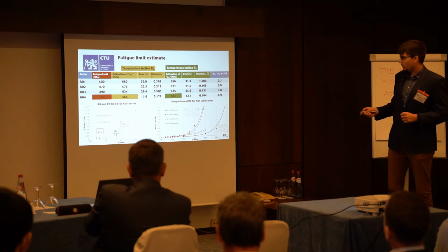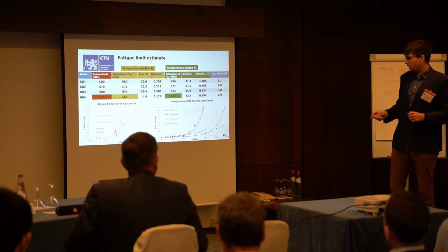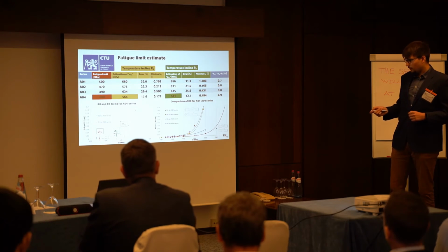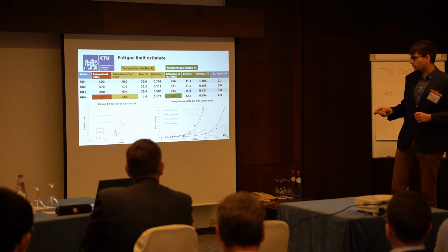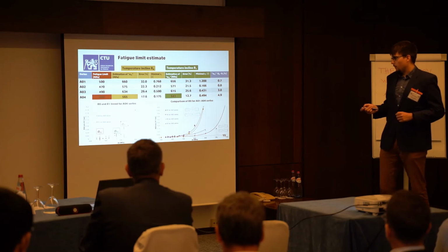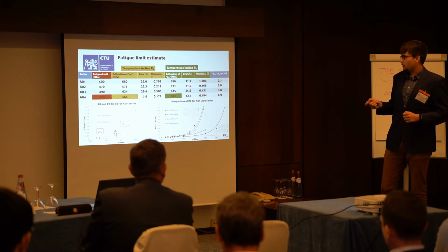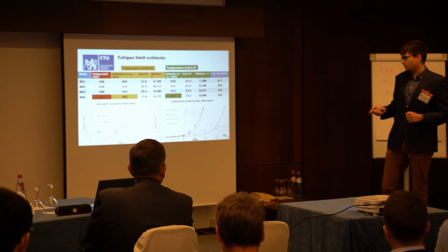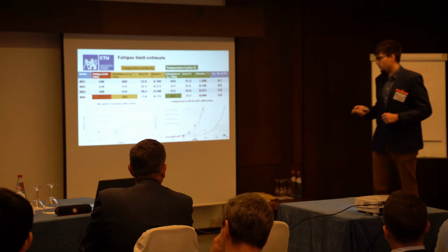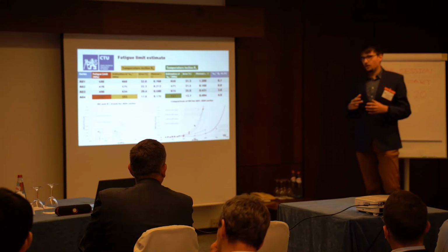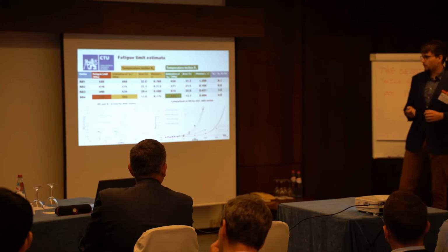On the right side, you can see the evolution of the initial incline for the dog bone specimen and for the hourglass specimen, and you can see that the active volume is leading to a much higher increase in temperature. Also, here you can see the radius, the initial incline and the secondary incline for the fourth series, which is the dog bone specimen with the higher diameter in the active cross-section.